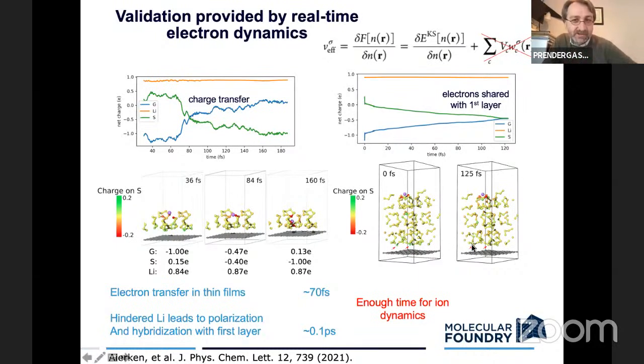That would be quite dangerous in this case, because you could have strong electric fields and this spontaneous arrival of charge, if you're using a common Fermi level for the entire system, that would lead to maybe some chemistry that would be enhanced or over-exaggerated because of this effect. And so that's something we're trying to mitigate against. And I'm always thinking ahead to the molecular dynamics I might run. And so I want to foresee what these problems are and try to avoid them.